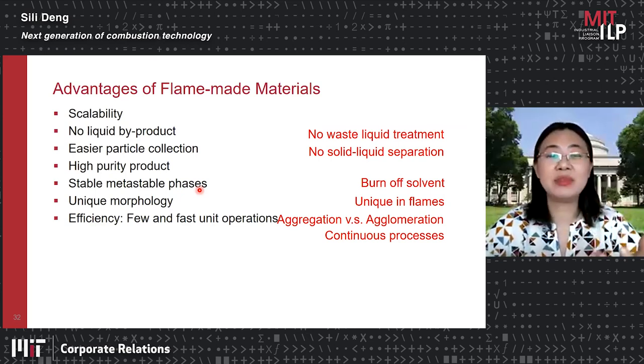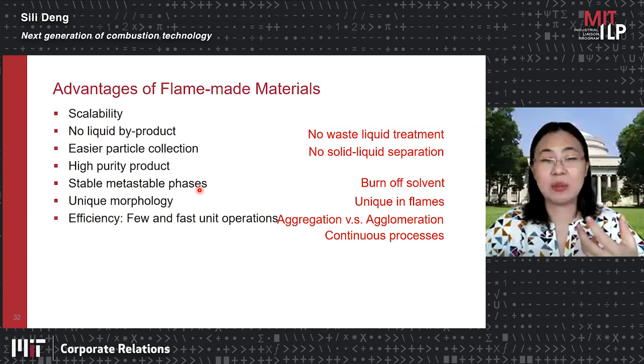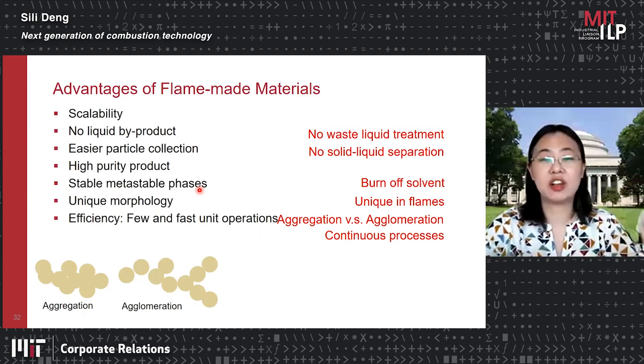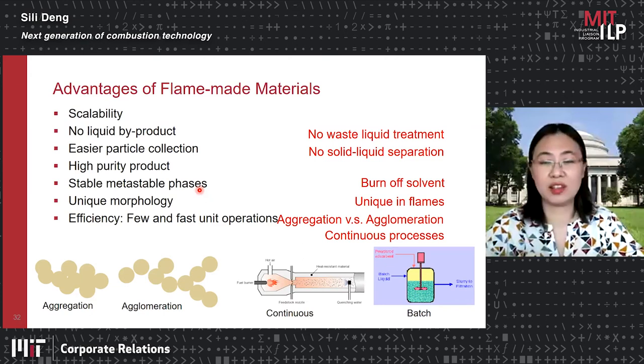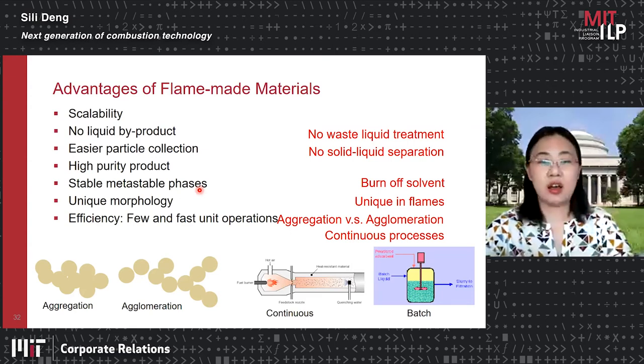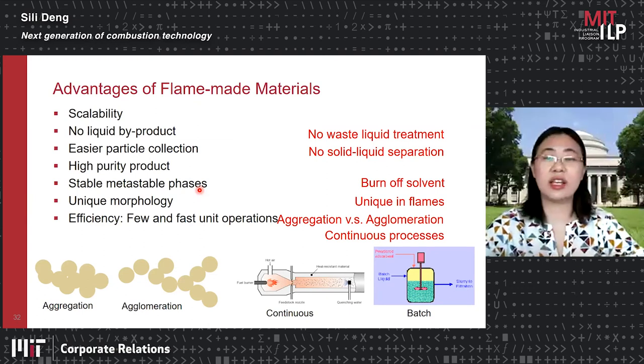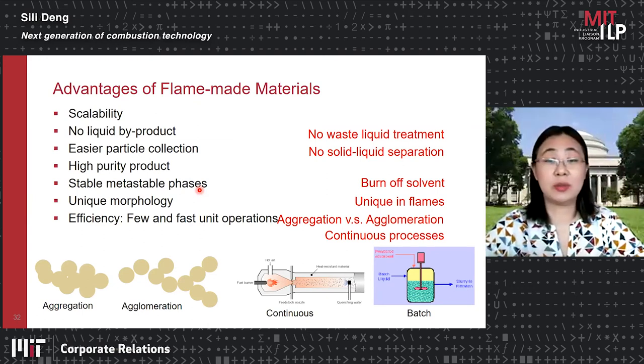And using flames, it's a really fast process, in several seconds compared to several hours or even several days of liquid wet chemistry. And you can achieve unique morphology by changing the combustion environment. And this is a continuous process where you can avoid the batch process, which will limit the efficiency. The continuous one can just run smoothly, so that the overall efficiency of the manufacturing should be very high.